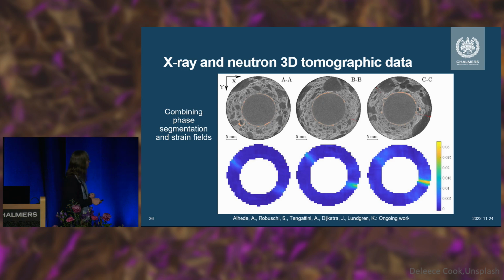And what is so nice is that through this displacement field, you can also derive the whole strain field. So you can view in different slices along the specimen how the crack looked. And here, for example, you see the strain localization due to the cracks. These types of contour plots are what we've typically been looking at from analysis for a number of years. But what we can do now is have experimental results to compare with, to be able to come back.